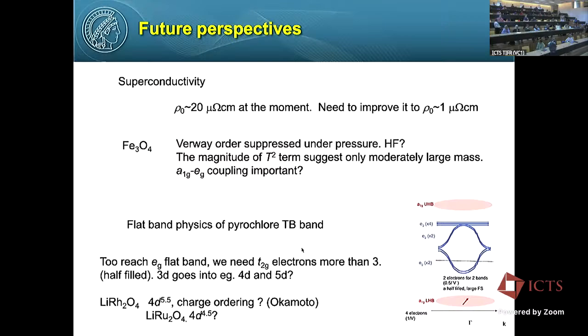Well, thanks very much, Hide. I was just wondering how robust is the geometrical frustration in the single crystal, because the strain that you've put on it with the film is quite large. Have you not yet done transport under applied strain to see at what point charge order starts to appear? We actually tried it first, but somehow my PhD student kept failing and he cried. And so that's why we moved to thin film instead. So you saw no direct effect? Of course, in our mind, perhaps our technique is not good enough. Somehow the crystal breaks before observing charge order. So we haven't seen charge order yet.